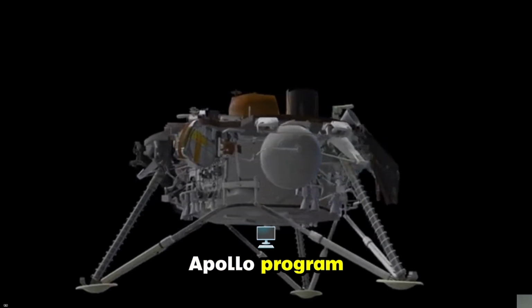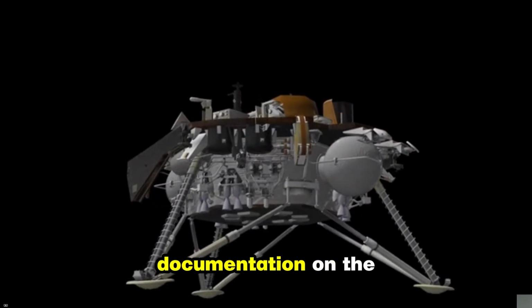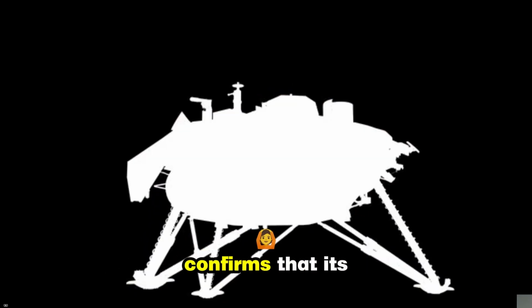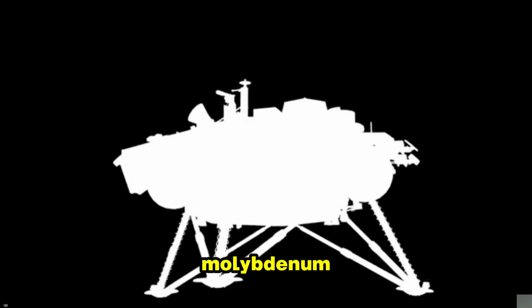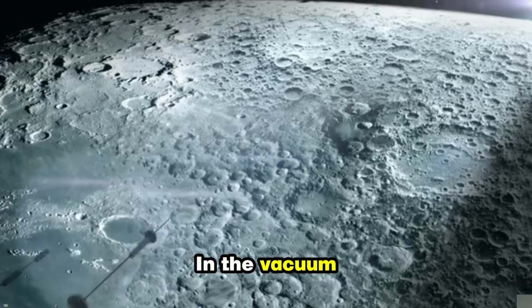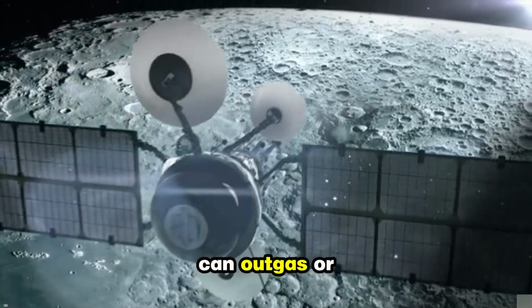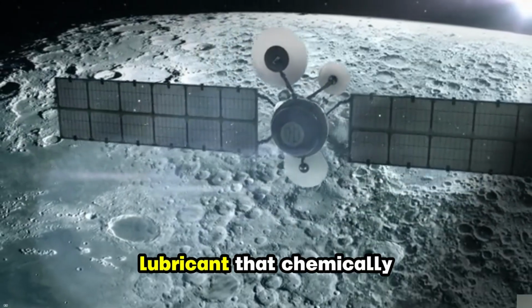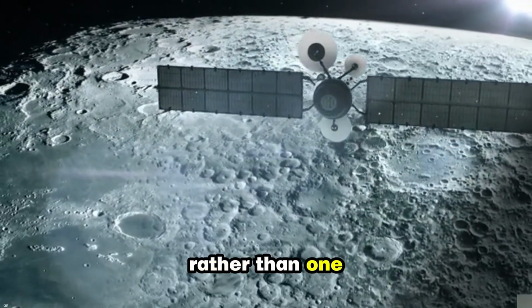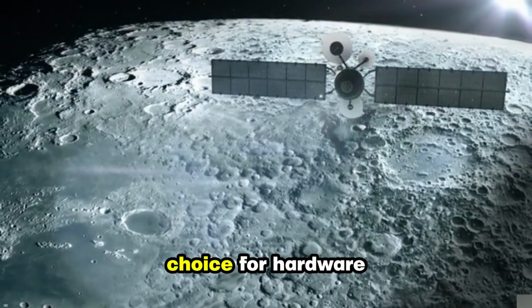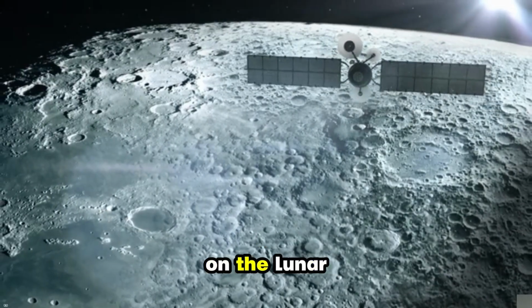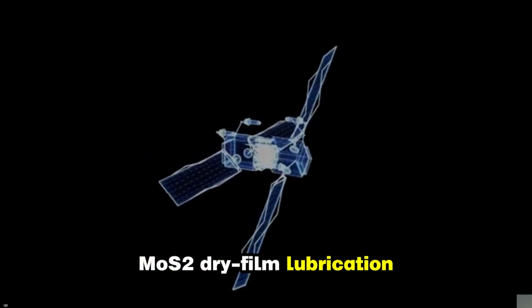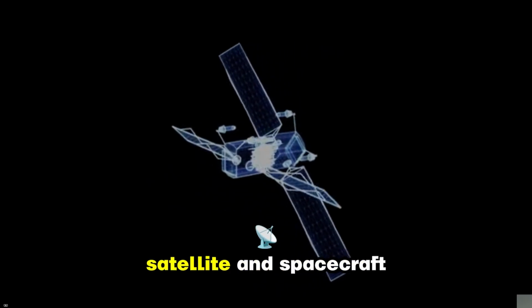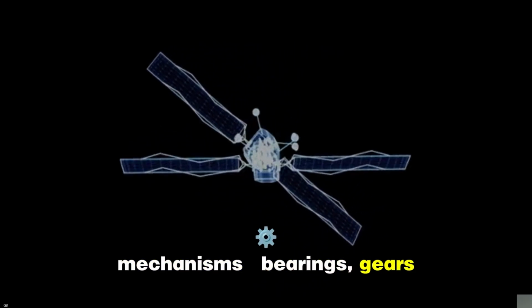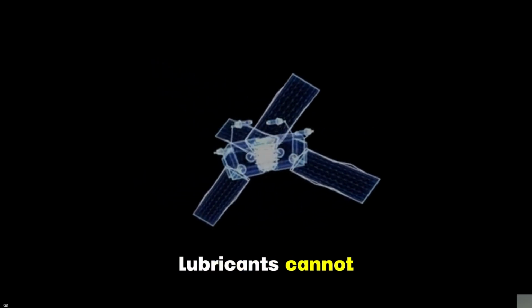That work paid off in the Apollo program. NASA's own technical documentation on the Apollo lunar module landing gear confirms that its mechanisms used a molybdenum disulfide dry film lubricant. In the vacuum of space, conventional oils and greases can outgas or break down, so a solid lubricant that chemically adheres to metal, rather than one that relies on a liquid film, was the practical choice for hardware that had to deploy reliably on the lunar surface. MoS2 dry film lubrication has remained a standard choice for satellite and spacecraft mechanisms, bearings, gears, gimbals, ever since, precisely because it performs where liquid lubricants cannot.